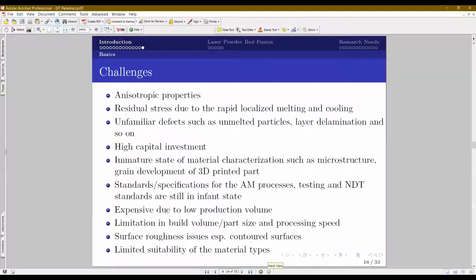Of course, any process comes with its own challenges. First and foremost challenge, anisotropy. Properties vary with the direction due to the grain orientation. And the second challenge is residual stresses because of the rapid heating and cooling. And unfamiliar defects. When I say unfamiliar, these defects are very peculiar and specific to 3D printing, which are not experienced in conventional processes.